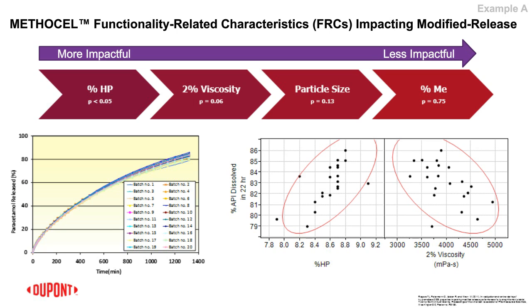And what you can see here lines up exactly with what we saw in the linear modeling. There is a pretty clear relationship between drug release at 22 hours and hydroxypropyl substitution. As we increase HP, we increase the amount of drug that was dissolved at 22 hours. As we increase molecular weight, or 2% viscosity, we decrease the amount that was dissolved within 22 hours.